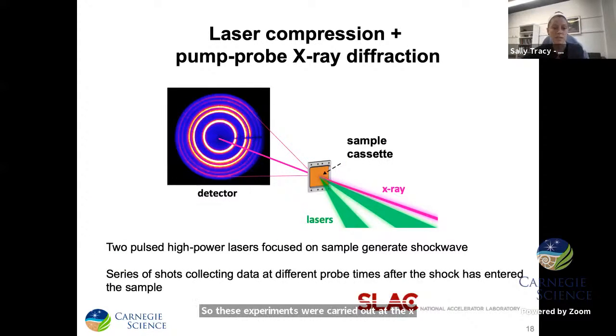So these experiments were carried out at the X-ray free electron laser at Stanford. Here in these experiments, we mount a series of silicon carbide samples on a sample cassette, which is then enclosed in our target chamber. Then we carry out a series of shots where we focus these 2 high-powered lasers onto the silicon carbide targets, and then collect X-ray images at different probe times after the shock has entered the sample.